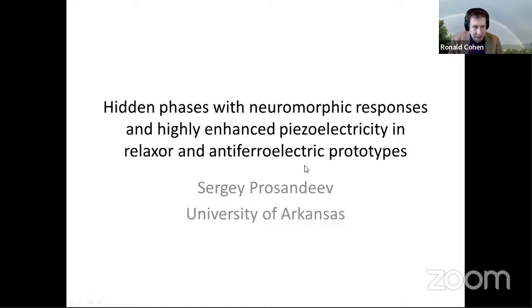So we showed some time ago that in pure PMN there's actually a ferroelectric ground state, and it just doesn't form because it's just hard to get it to form. But, at least in simulations, if we apply even a static electric field, then we get a polar state. And we did some MD simulations as a function of both temperature and electric field, and actually mapped out a phase diagram for that. So what you're calling a hidden state,